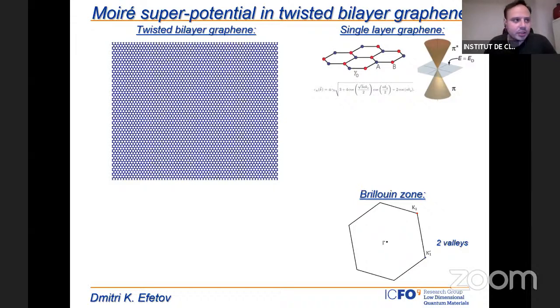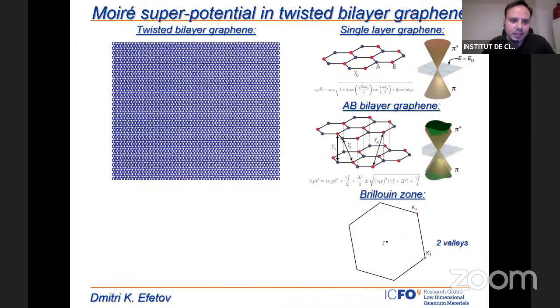But again, what one can do is one can actually look at also bilayer graphene. So what happens if you have 2 perfectly aligned graphene sheets? So basically, this is how naturally occurring bilayer graphene looks like. So we call it the AB bilayer graphene. And you can really think of it as two carbon sheets just basically on top of another. If we look now at the band structure calculations, first of all, we have now a more complicated unit cell. So we have now 4 carbon atoms in the unit cell, 2 in the bottom layer and 2 in the top layer. And we, of course, have now many more hopping terms between those layers. And what this gives us now, if we do the tight binding calculation, is 4 bands. And these bands are actually not Dirac-like anymore, but they're parabolic. So basically, close to 0 energy, these can be approximated with a parabolic dispersion relation.